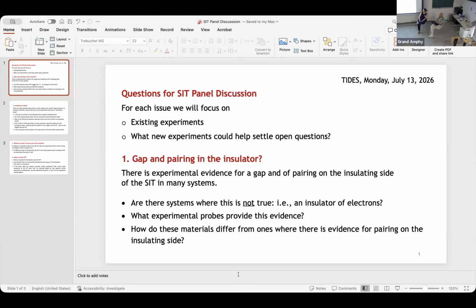So you shine on a sample at dilution range temperature, which might be a sensitive guy. So what do you really measure? It's like you measure a sensitive Josephson junction that you open to light. Might be difficult also, and dilution would be difficult. Maybe a little higher temperatures would not be that difficult, but someone will have to try. If your TC is 3 degrees, so if your superconducting is few degrees, you don't need to go to dilution.